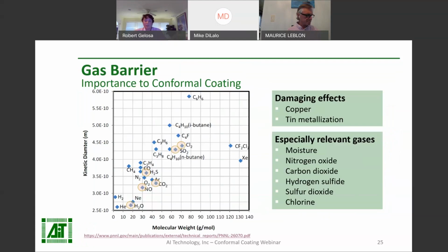When harmful gases combined with moisture penetrate a conformal coating, they can cause massive corrosive damage to the board. We see a few harmful gases highlighted in this chart: chlorine, sulfur dioxide, carbon dioxide, hydrogen sulfide, and nitrogen oxide, along with moisture. As all of these other gases have a greater kinetic diameter than moisture, a coating effective in blocking moisture will also be effective in blocking the other corrosive gases. That's why AIT conformal coatings can prevent more corrosion than other conformal coatings, by blocking the diffusion of these corrosive gases and moisture.